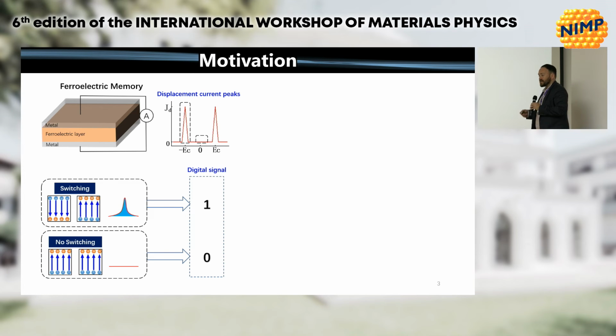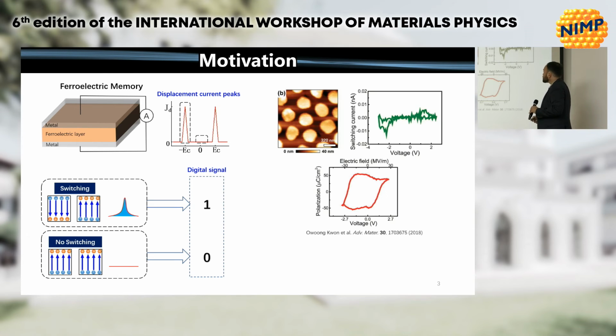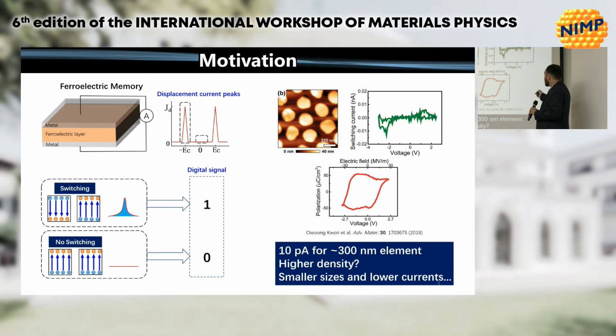So in terms of motivation, it's not a great motivation, but I'll tell you our motivation in terms of ferroelectric memories. And don't ask me the device that would be done with this, because I don't really know. It's a bit of a stretch. But if we think about ferroelectric memories, we have the idea of course, switching the material, and we can detect whether or not something is switched, if the domain is switched, by looking at the displacement current. So in this instance where we have a displacement current, that could be a bit of 1. Now, as we go to smaller and smaller elements, the detectable current becomes smaller and smaller. So if we go to smaller and smaller elements, this is going to be very difficult to detect. So this is 10 picoamps for 300 nanometers. And if we go to even higher density, for higher density storage, we'll have smaller sizes and smaller currents.